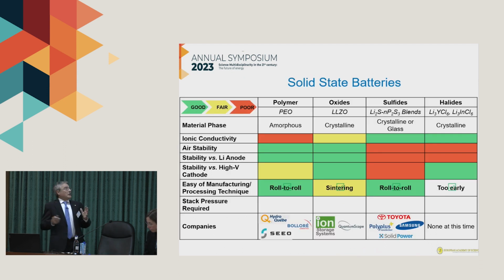There are different solid electrolytes. In solid-state batteries, we use solid electrolytes: amorphous polymers, and inorganic solid electrolytes, oxides, sulfides, halides, all of them crystalline, and the polymer. All of them have advantages and disadvantages. In the case of polymer, the ionic conductivity is very poor. On the contrary, in the sulfides, it's excellent. But in the polymer and oxides, the air stability is really good, but not in the case of sulfides and halides.